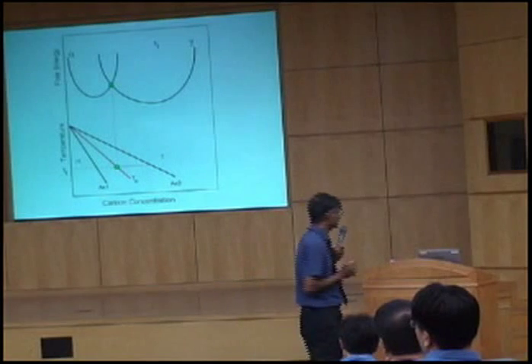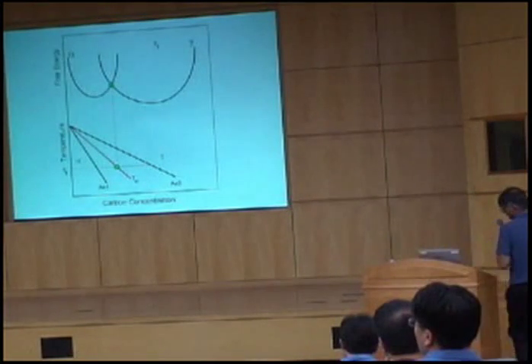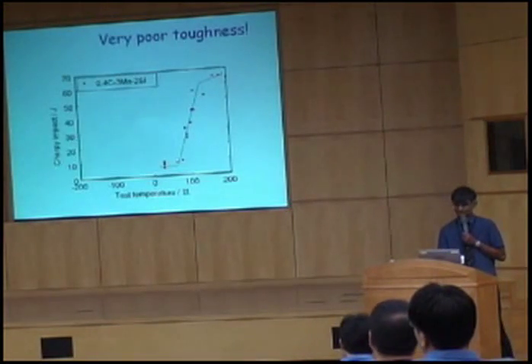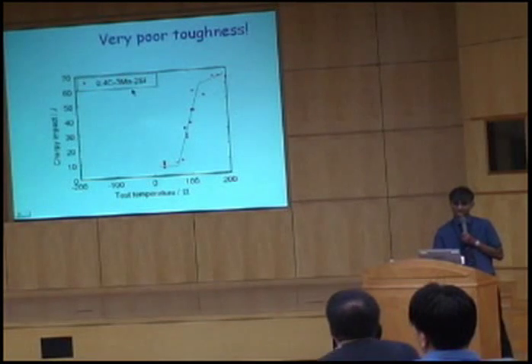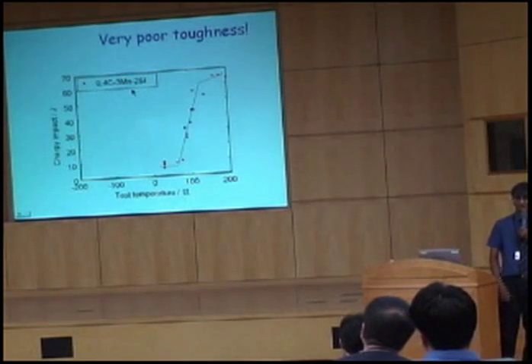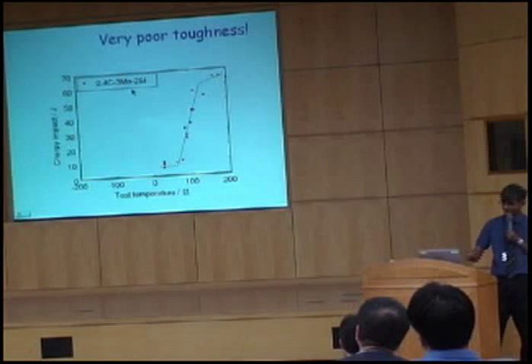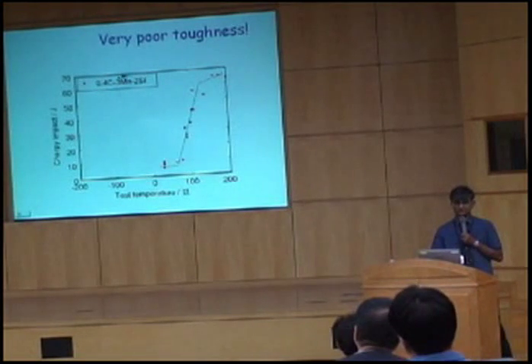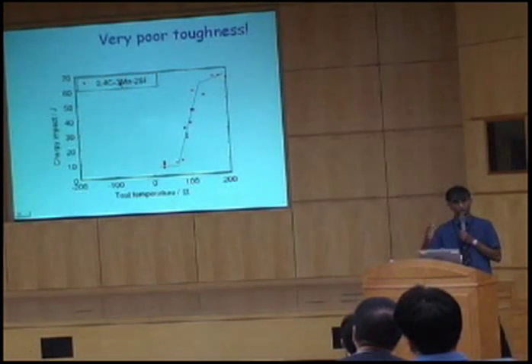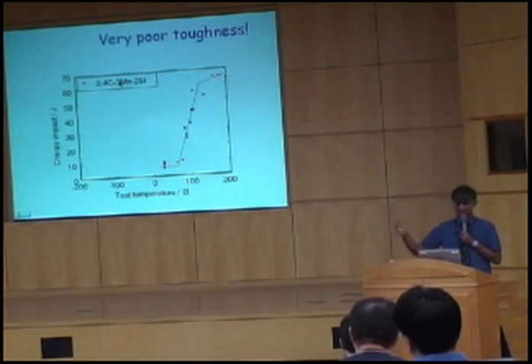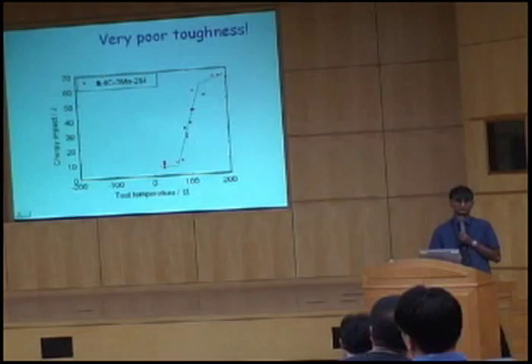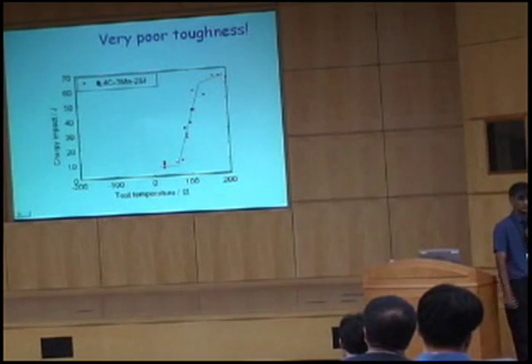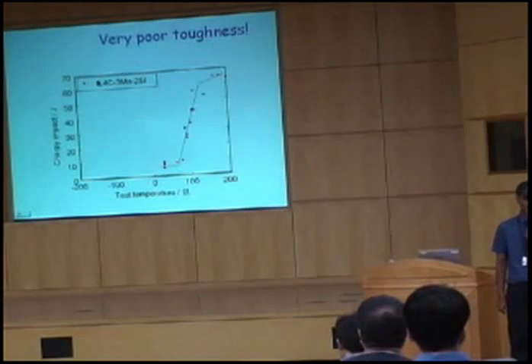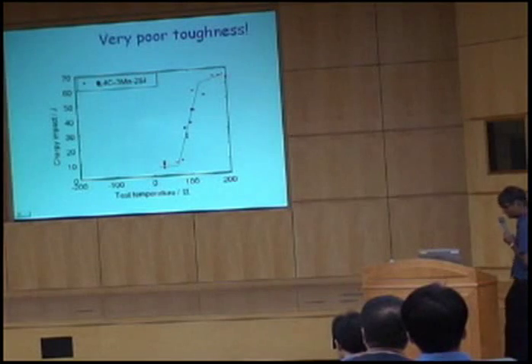So what I'm going to do is I'm going to show you this alloy here, which has very poor toughness, and I'm making two new alloys. One in which I change the substitutional solute to move the T0 curve to higher carbon concentrations. Okay? And the second one in which I reduce the carbon concentration by a factor of 2 without losing any strength. And let's see how the toughness changes.